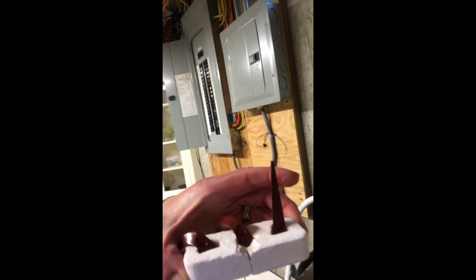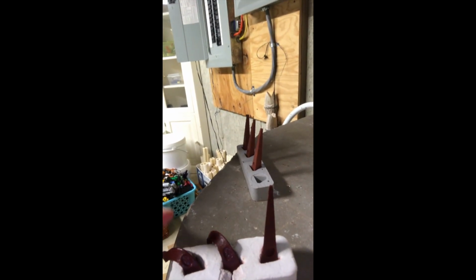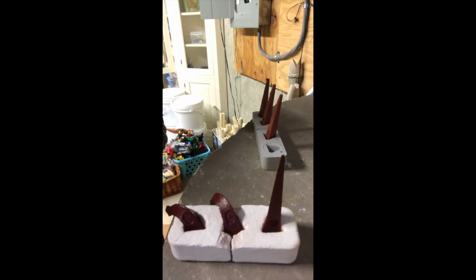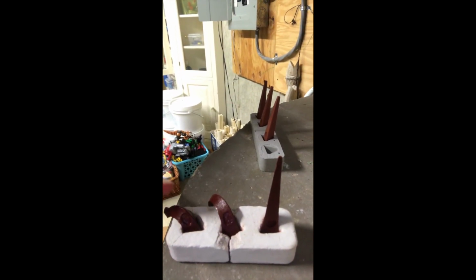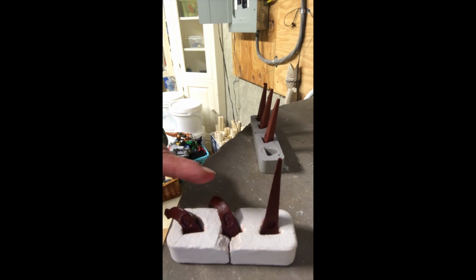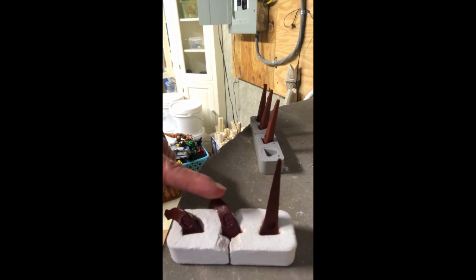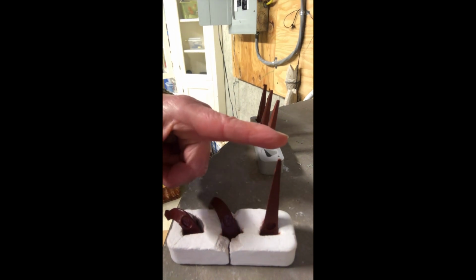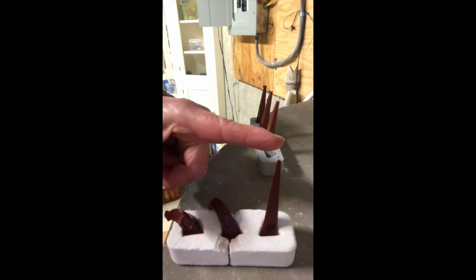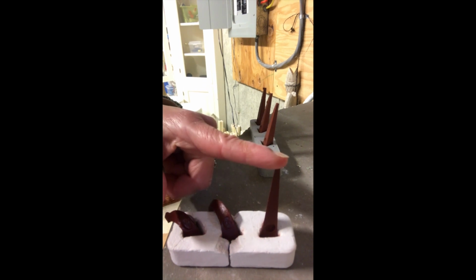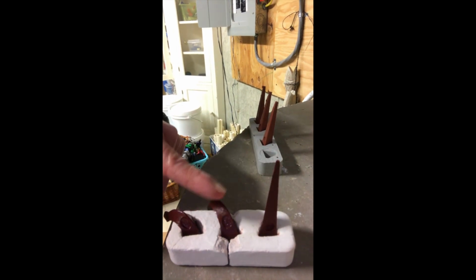When the firing is complete and my kiln is off and cooled down and I open it up, this is what I am looking for. So these are 3 cones from my last firing, a cone 07, 06, and an 05. These witness cones tell me that my kiln got hotter than 05. The target goal temperature was 06, and it didn't quite reach the temperature of 05, which is hotter than what I needed.